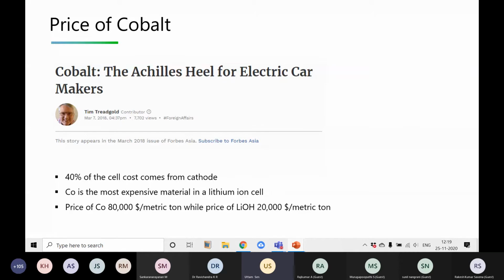But the material, you can see 40% of the cost of the cell is coming from the cathode, and the costliest part is the cobalt. Cobalt is like $80,000 per metric ton. Compared to lithium, it is like 4 times, and the amount of cobalt we are putting in is much more compared to lithium. So that is the costliest part in the electric vehicle.